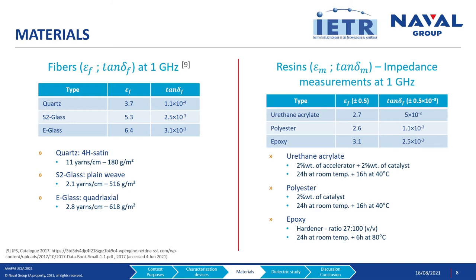To make a composite laminate, we have to associate these fibers with thermosetting resins. We selected three natures of resin: urethane acrylate, polyester, and epoxy resin. We cast these resins into silicon molds and measured the dielectric characteristics by impedance measurements. At 1 GHz, these resins highlight relative permittivity epsilon-m from 2.6 to 3.1 and dielectric loss tangent delta-m from 0.005 to 0.025. Already from this data, we can see that quartz fibers and urethane acrylate resin present the most interesting dielectric characteristics for the targeted applications.